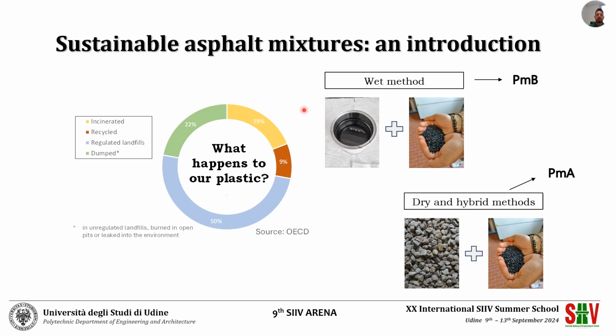Plastics can be incorporated in asphalt mixtures through three different technologies. In the wet method, low melting plastics are added and mixed directly to the bitumen until a homogeneous binder phase is achieved. In the hybrid and dry methods, high melting and low melting plastics are added to the mixtures, modifying not the binder phase but the entire mixture.